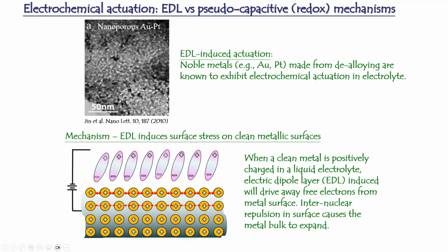But to magnify this effect, they have to increase the surface area to volume ratio. That's why if you have a bulk piece, if you take your wedding ring, it probably won't work. You have to dramatically increase the surface area to volume ratio. And how do they do that? They turn the material into some nanoporous structure. So how to make these materials? They use a eutectic material system and etch away one of the phases. After you have done that, you have all these nanopores. The pore size is a few nanometers. Therefore you have a gigantic surface area to volume ratio, and therefore the EDL actuation could be rather large, as you have seen in the atlas that I have shown just now.